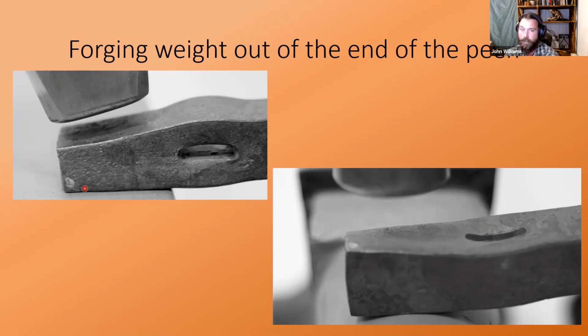Well, I know that I'm going to exceed that if I go to 3/8 first. If I go to my 3/8 inch width, then I'm already at 1 inch. And as soon as I exceed that, when I try to bring it back to 1 inch, I'm going to be having to struggle a little bit. So what I'm going to do in advance, this is some forward thinking, is narrow that end so that by the time I bring it to its 3/8 inch dimension, it will widen to the desired end. So I'm going to bring that down roughly to 3/4 of an inch. And by the time I bring it to this stage on the bick and take it to 1 inch wide, it will be about 1 by 3/8 by the time I'm done. So again, 3/4 of an inch here.